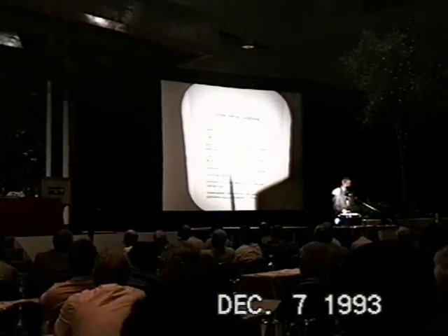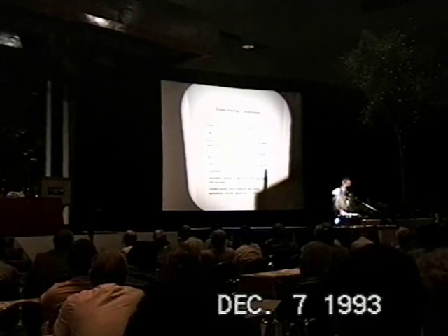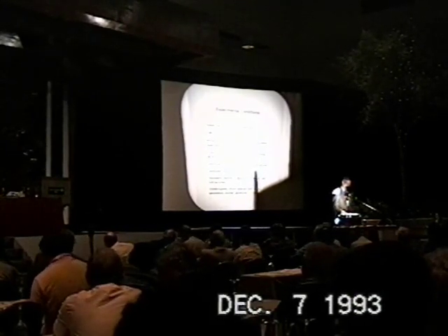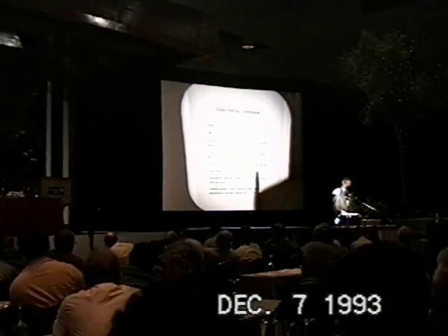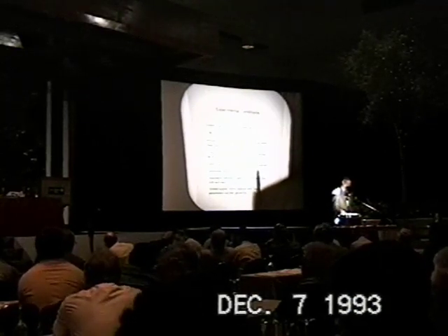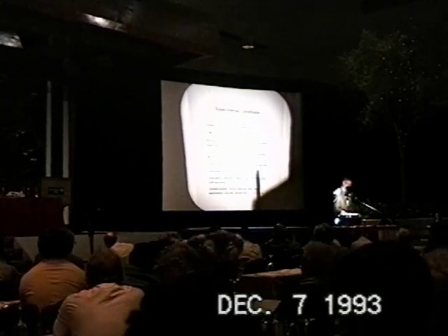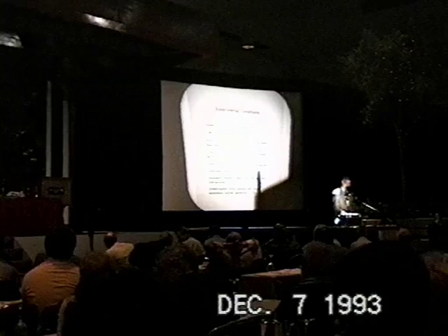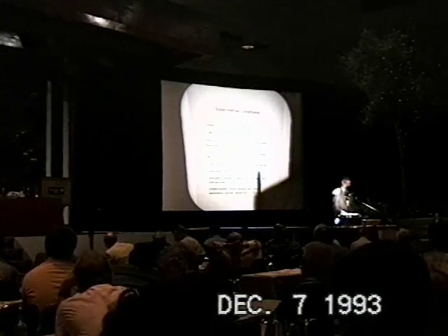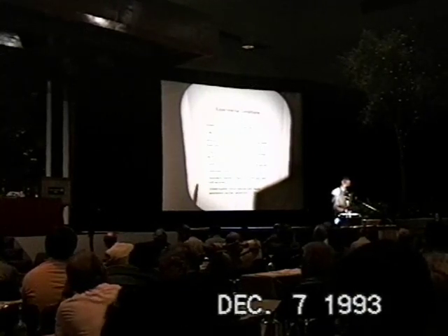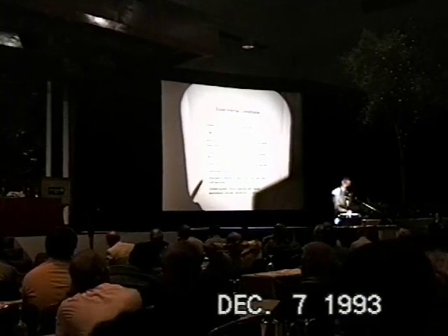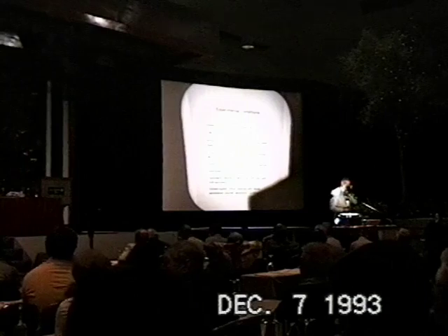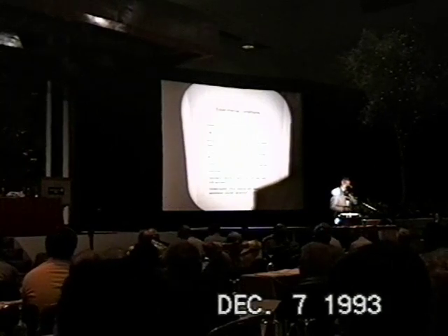We noticed that when we went to larger current densities, we could not reproducibly obtain loading ratios of 1. We did on some occasions go afterwards, after we had obtained loading ratios of 1, to current densities in some cases as high as 1 amp per square centimeter. We used a controlled temperature water bath of 27 plus or minus typically 500ths of a degree centigrade.